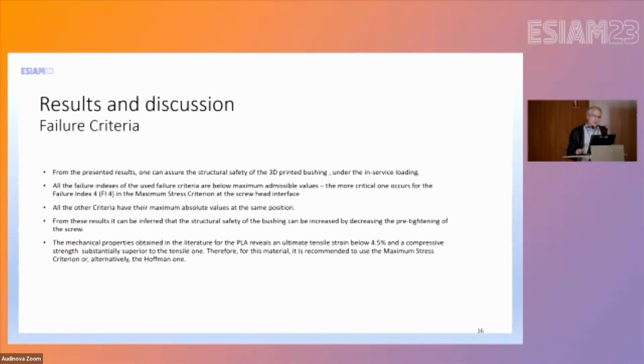From the presented results, one can assure the structural safety of the 3D printed bushing under the in-service loading. All the failure indexes of the used failure criteria are below the maximum admissible values. The most critical one occurs for failure index 4 in the maximum stress criterion at the screw head interface. All the other criteria have their maximum absolute values at the same position.